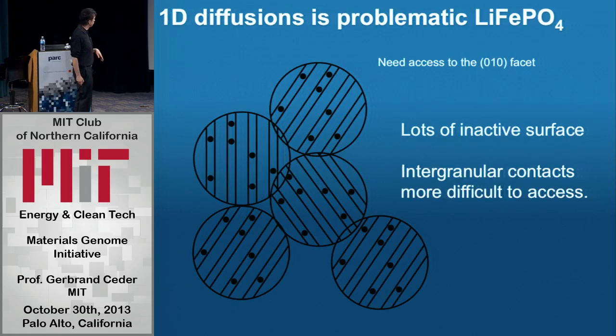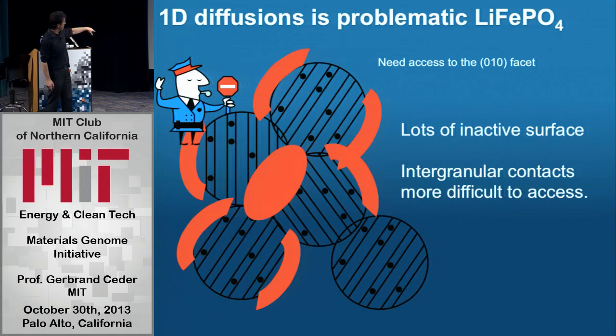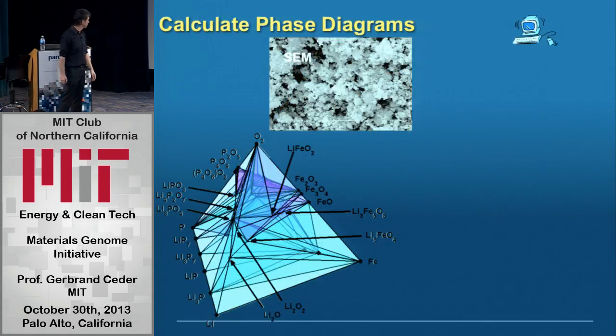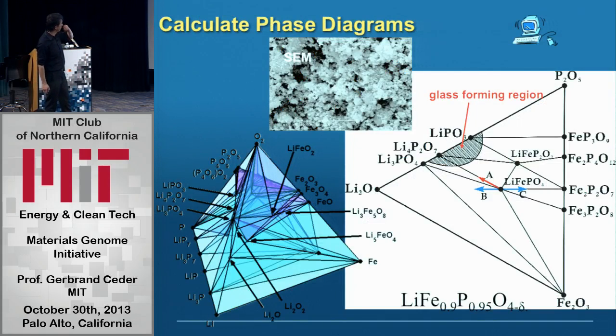So what we learned to do was essentially engineer the microstructure between particles. What we found is that the slow paths were actually the interfacial contacts between particles. So we tried to put a fast ion conductor on there, so that we could get very fast lithium-ion conduction through these particles. We did that through phase diagram engineering. We put an amorphous glass, a pyrophosphate glass, which is in that shaded region there, on the particles.